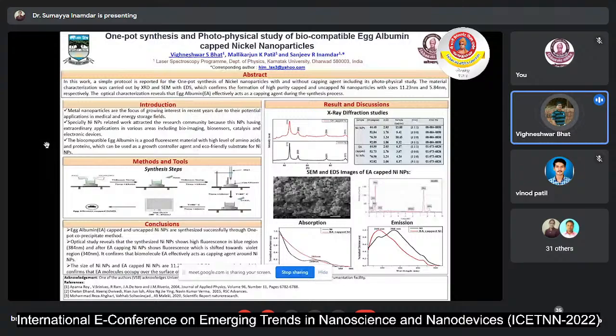In XRD analysis, I have confirmed that the undoped, that is uncapped, nickel nanoparticles have a size of 11.23 nanometers. The egg albumin capped nanoparticles show a size of 5.84 nanometers.